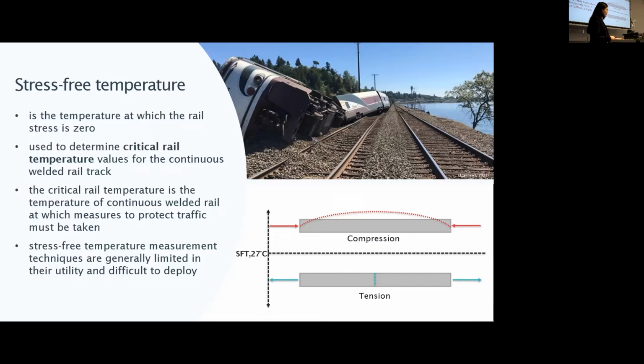So as you can see in the diagram, while the rail temperature remains below the stress-free temperature, the rail will be in tension. And as the rail temperature rises above the stress-free temperature, internal compressive stresses begin to develop. Large internal tensile or compressive forces can lead to rail breaks or track buckles. And it can happen when the internal forces are sufficient to overcome either the local tensile strength of the rail or the lateral restraint to buckling provided by the track system.